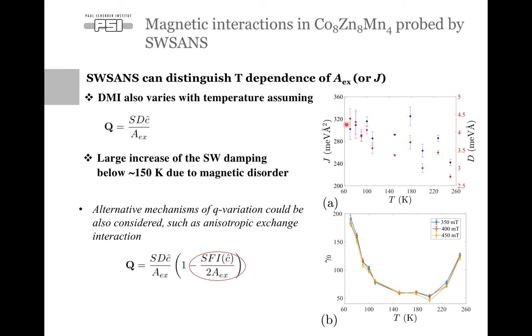However, analysis of the lower temperature data is very complicated or even impossible because of the large damping and very low signal at lower temperatures. And also from this dependence, we can calculate the Dzyaloshinskii-Moriya parameter using the famous formula from the Bak-Jensen model, just having the exchange stiffness and the spiral Q vector. We can calculate the Dzyaloshinskii-Moriya parameter, and it's shown here. And interestingly, we see that in order to satisfy this formula and describe the spiral pitch change on cooling, we also have to introduce the temperature change of the Dzyaloshinskii-Moriya interaction.